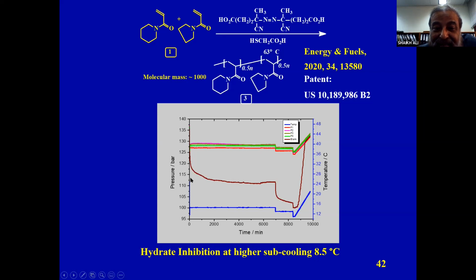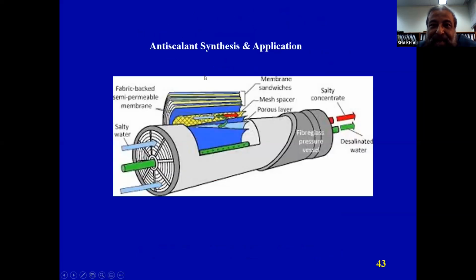Why? The company said that it can work up to 8.5 degrees centigrade cooling temperature. But most of the commercial ones work up to 12 degrees centigrade. This is the one we made at number 65, the last sample we tried, and this worked, one of the best in the world, which we got a patent on and we published. And this is obtained by free radical addition polymerization of these 2 monomers. And this is kinetic hydrate inhibitors.